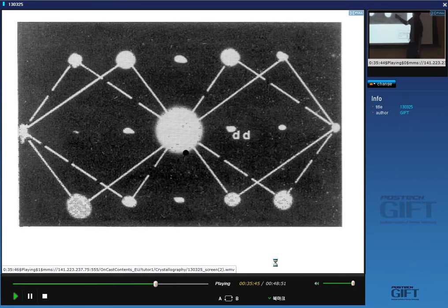But here's another rotation of 180 degrees about this axis. That would also do it. Or a rotation of 70.52 degrees about this would do it. So I've already identified three axis angle pairs which exactly describe the relationship between these two crystals. The angle here was 180 degrees about the 112. If I take it through the plane of the board, it's 70 degrees about 110. And those are exactly equivalent operations.